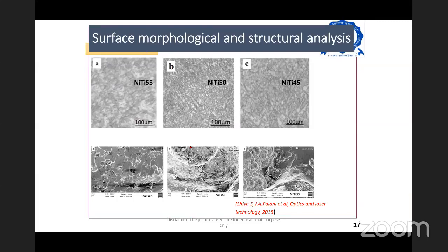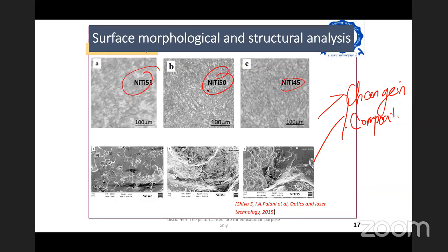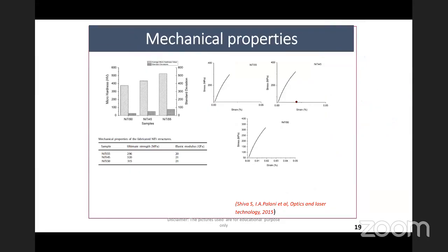In fact, these are some of the porous structures which are available. But the good part with this system is you have a configuration to investigate the influence of change in composition. In our case, we changed the composition by changing the nickel titanium percentage, like NiTi 55, NiTi 50, and NiTi 45, and we went for the different characteristics. These are the different mechanical characteristics which we have employed, and with respect to these, we studied the ultimate stress and the elastic modulus.